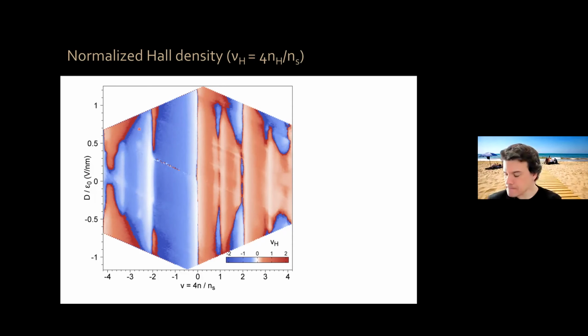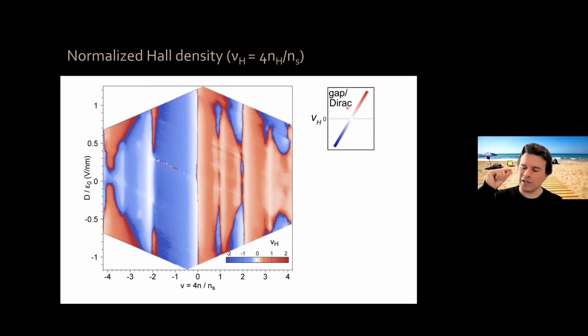Now, to 0th order, most of the features that you see in this phase diagram can be attributed to one of the following three features. One is a gap/Dirac point. When you reach a gap or a Dirac point, your density of carriers goes to 0. So your Hall density, which tells you the density of free carriers, goes to 0.